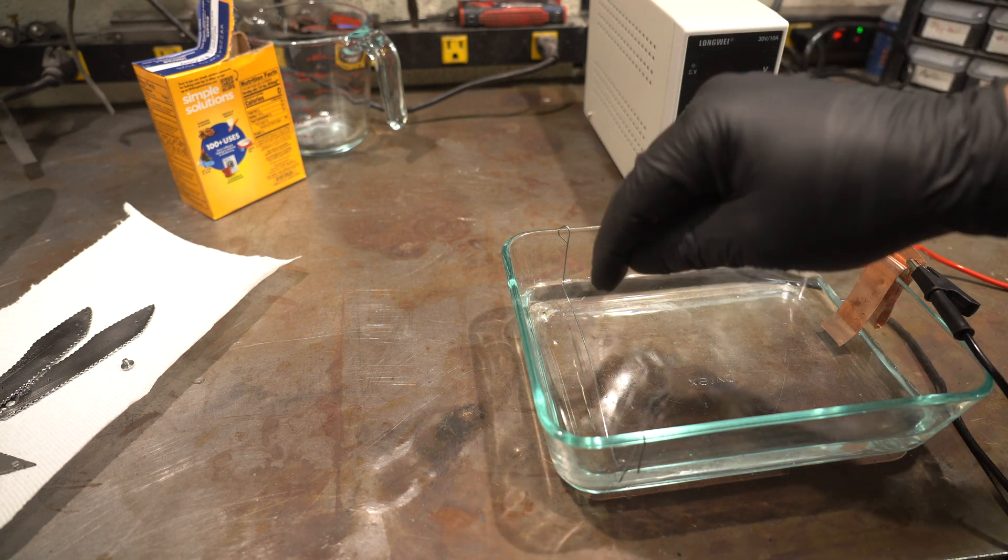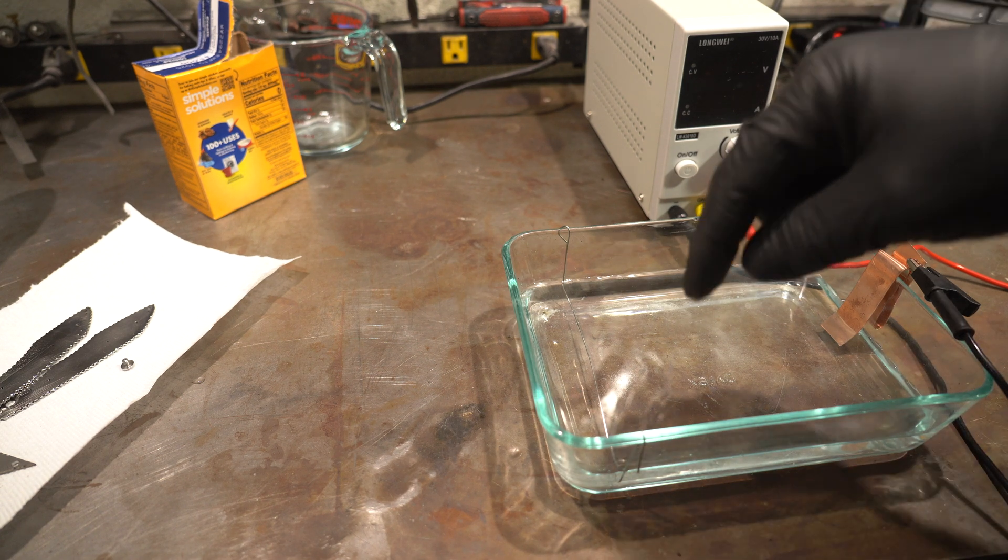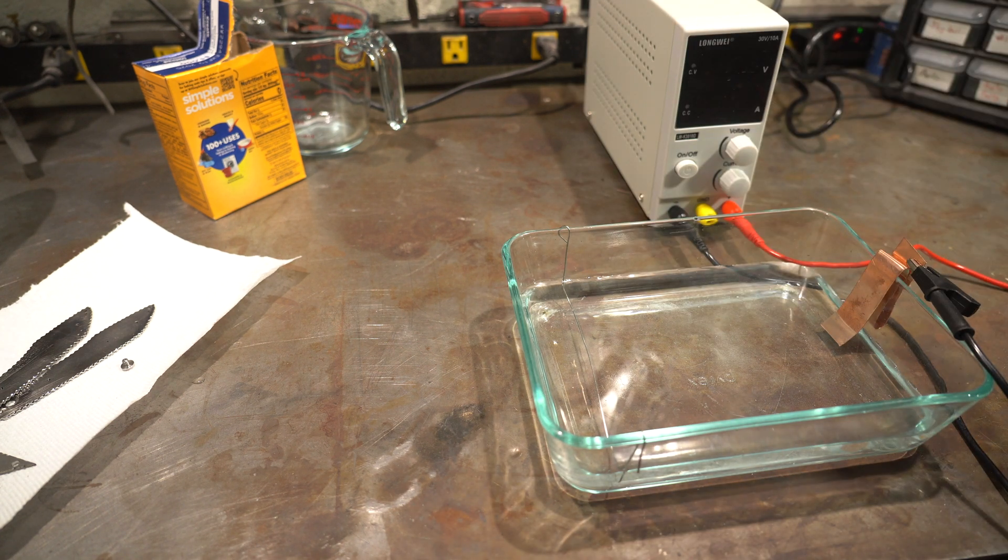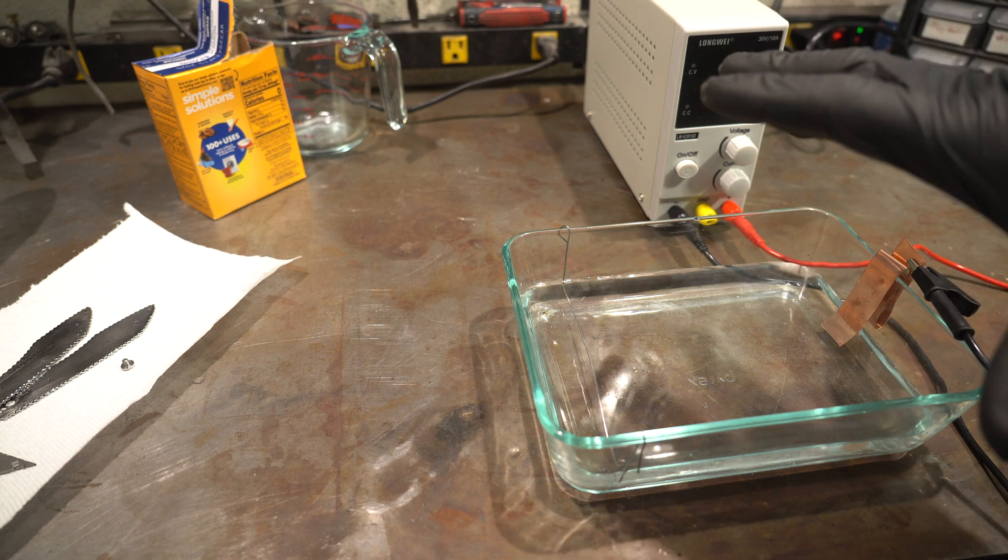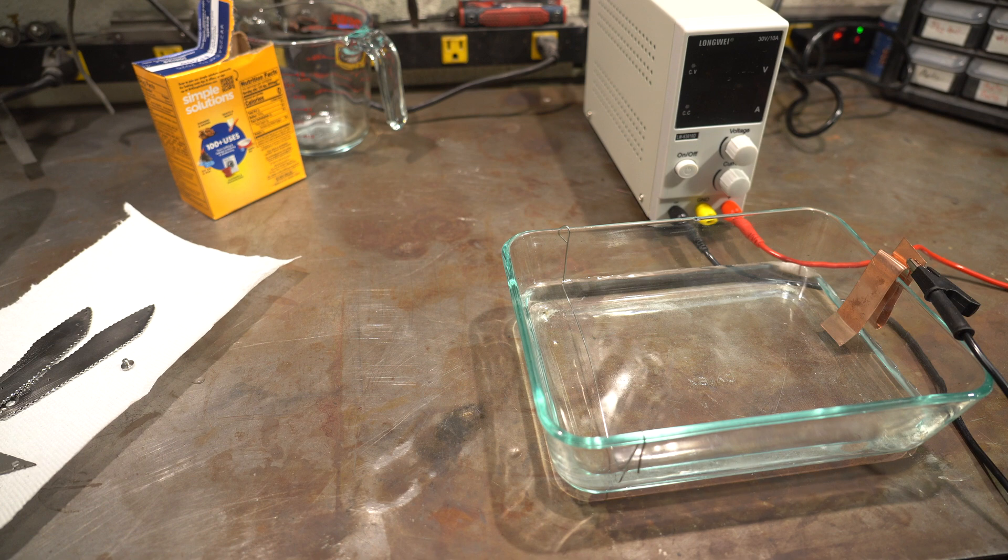For the other one that the pieces are actually going to connect to, this is a piece of titanium wire. So I'm going to put a test piece in here first before my actual pieces and connect it, and I'm going to run this around 13 volts because I want a copperish color. So let's try it.